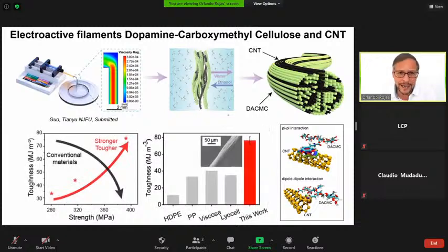And this is very nice because the filaments that are produced are quite tough. What you see in the red line there is how we can increase the toughness without compromising the strength. And this is a property that usually goes in the opposite direction, right? You can gain strength, but then you reduce the strain or extensibility of the material. But for some reason that I cannot explain, we get materials that are not only stronger, but tougher. And they are very competitive. If you see the image on the bottom right, of how that compares with filaments produced from polypropylene, viscose, or lyocell. Very interesting material. But what is new is that these are conductive as well.